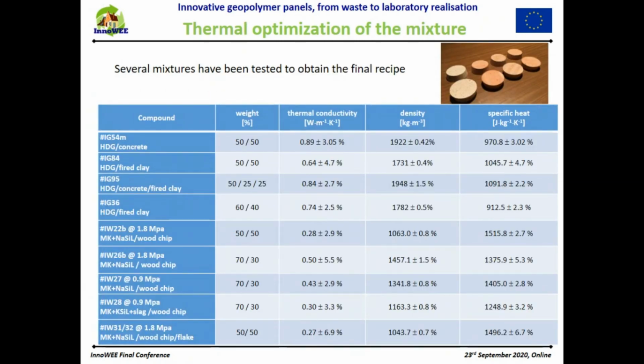We have measured a wide range of mixtures, and on the image on the top right, you can see some examples. We have found that the high density geopolymer can reach very high thermal conductivities. We are in a range of almost 0.91 watt per meter Kelvin. That is 3 or 4 times higher than the standard value of the plasterboard that is commonly used for radiant heating. Also, wood geopolymer could reach quite good thermal conductivity values. And the thermal capacity, the product of specific heat and density, can be very high for the high density geopolymer. And as said, this could be beneficial for the thermal inertia of ETICS panels.